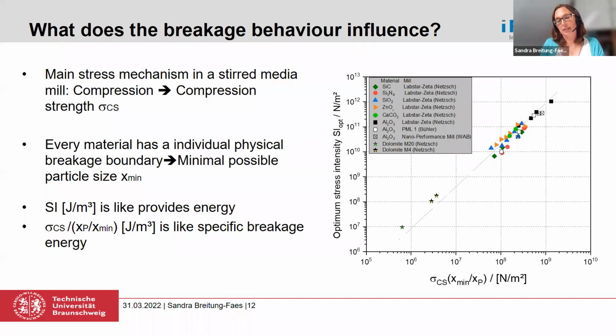So I said, okay, with this model, it seems to be possible, if you know your material parameters, to estimate the optimum stress energy. Later on, we had these two master theses with the dolomite grinding. And I said, okay, I have a look at the data, not so many experiments, but I found some optimum values, which were here, just to prove if it's possible to extend at least this model to coarser particles. Because here we ground the particles, let's say in the tens to ones of micrometer range. And here, these are really all particles below 1 micron. So it seems to work.